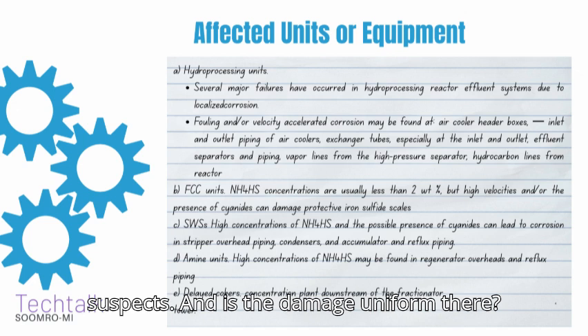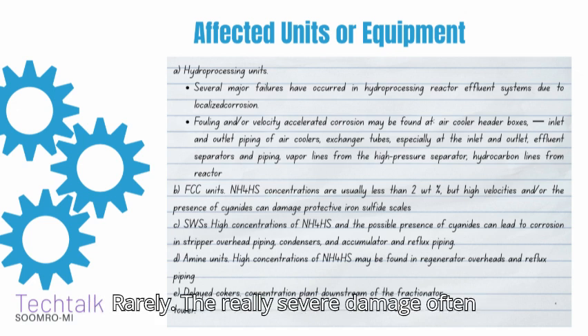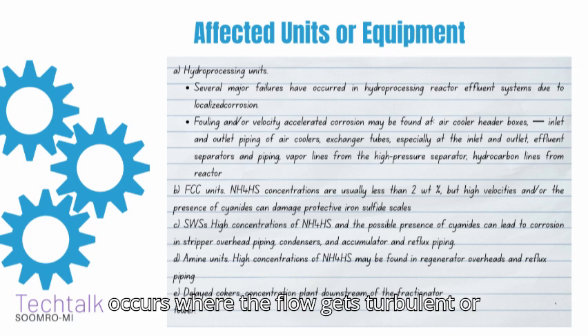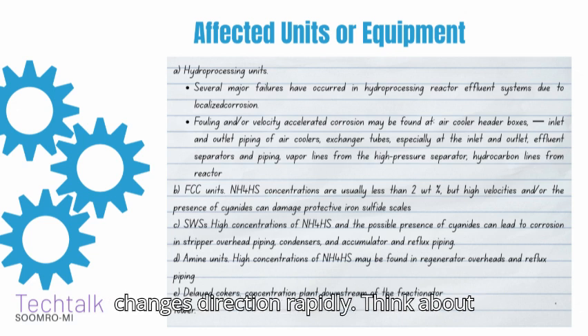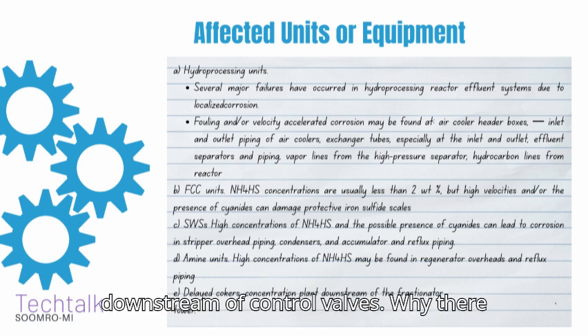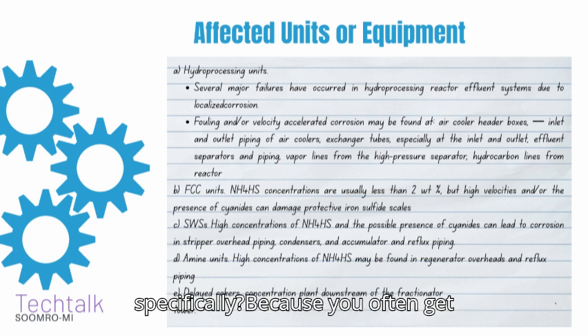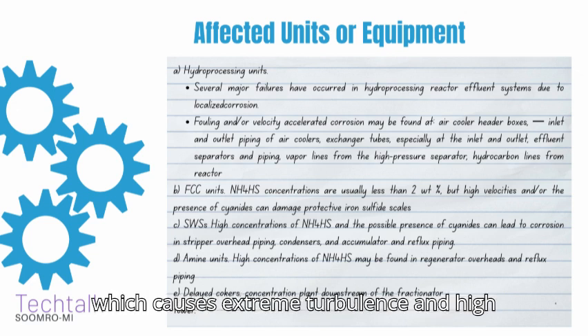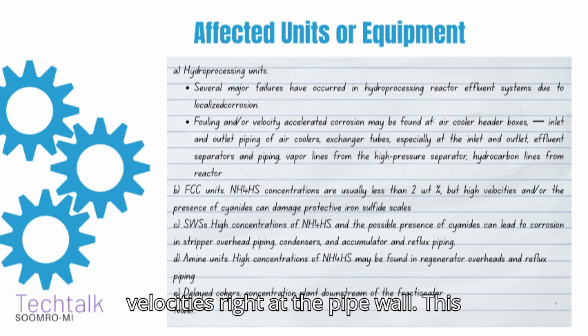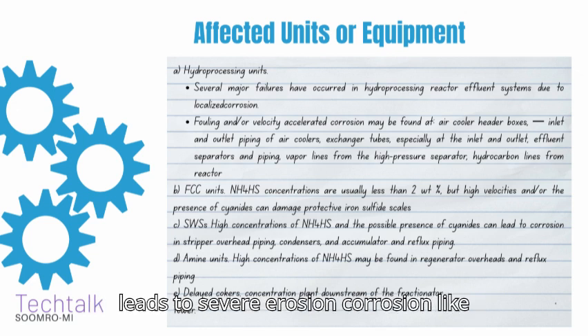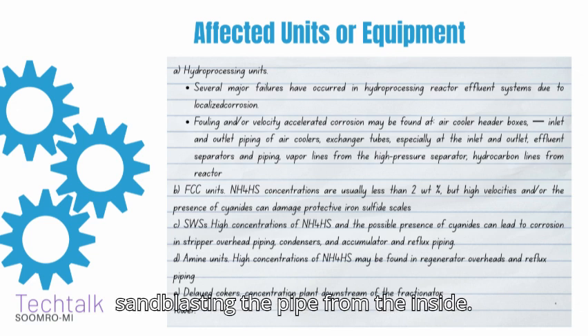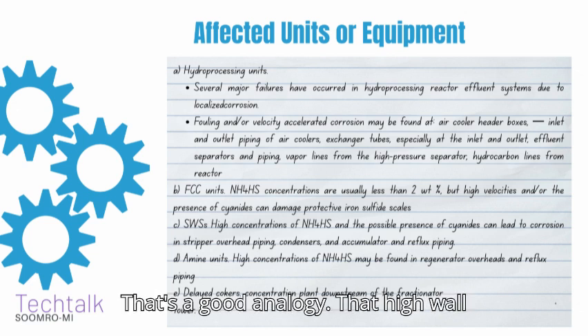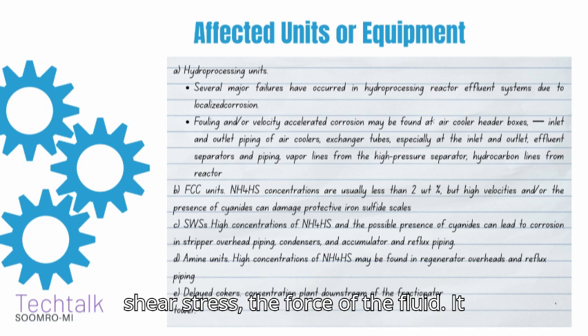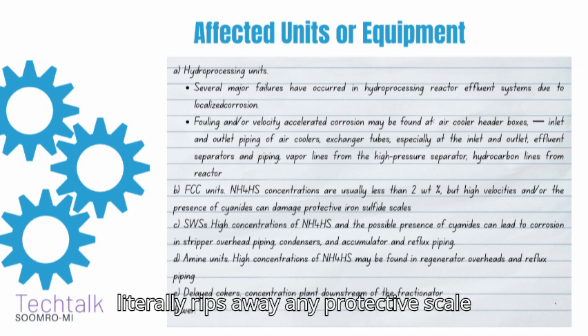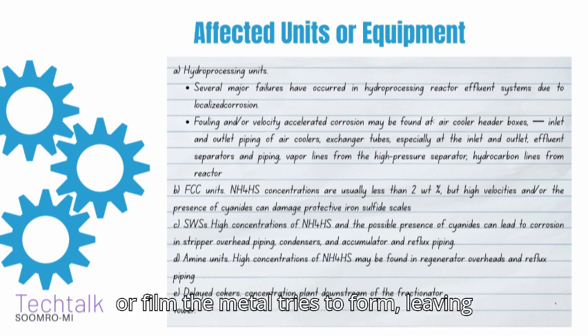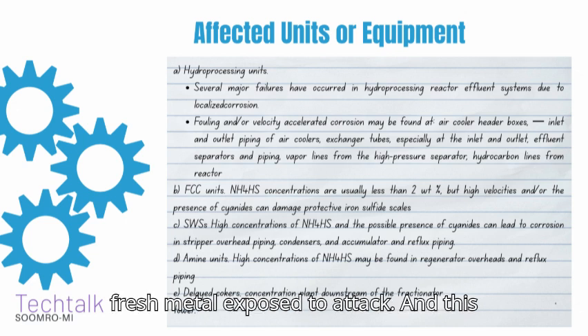And is the damage uniform there? Rarely. The really severe damage often occurs where the flow gets turbulent or changes direction rapidly. Think about downstream of control valves. Why there specifically? Because you often get flashing liquid turning rapidly to vapor, which causes extreme turbulence and high velocities right at the pipe wall. This leads to severe erosion corrosion. Like sandblasting the pipe from the inside. That's a good analogy. That high wall shear stress, the force of the fluid, it literally rips away any protective scale or film the metal tries to form, leaving fresh metal exposed to attack.